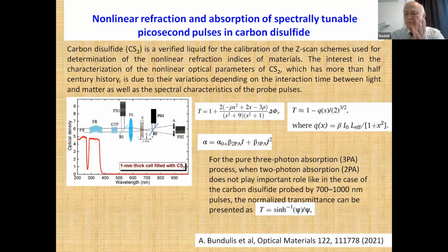effect starts to appear, which is 3-photon absorption, which is rarely seen in other materials. In some cases 3-photon absorption becomes stronger than 2-photon absorption, and it becomes especially strong in the case of near-infrared radiation above 1000 nanometers, for which we use some specific formulas to fit the results and analyze the characteristics of 3-photon absorption.